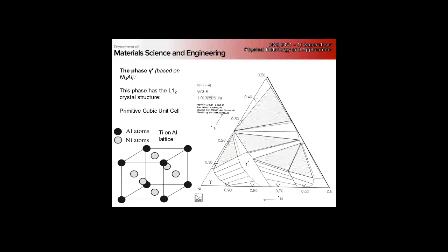So here's the gamma prime structure. The important thing to notice about this is the L12 crystal structure - it's an ordered compound, a true ordered structure. We saw a little bit of titanium with an ordered structure, but when we talked about steel and aluminum, we talked a lot about particle strengthening, but they were not ordered. We either talked about intermetallics like cementite, but we didn't really talk about ordered compounds.